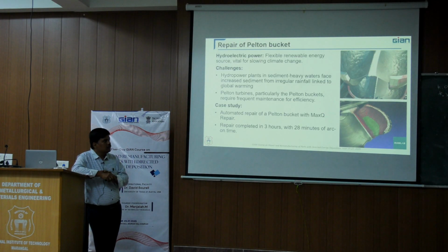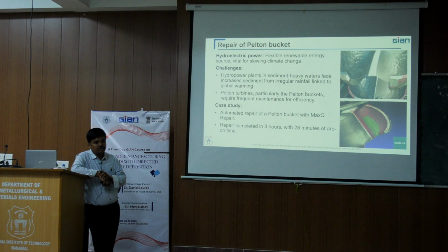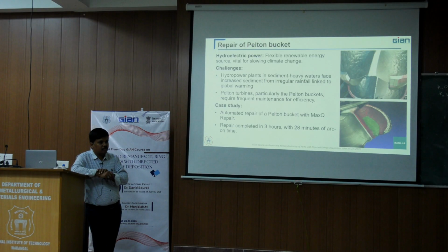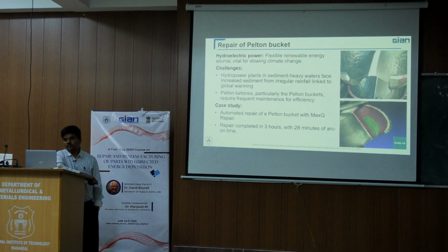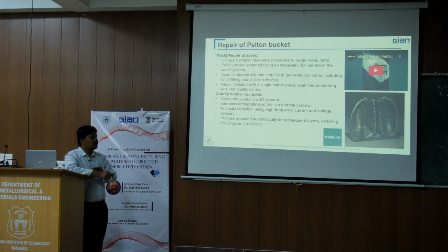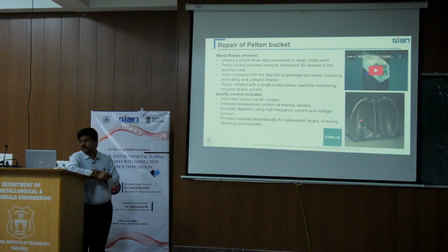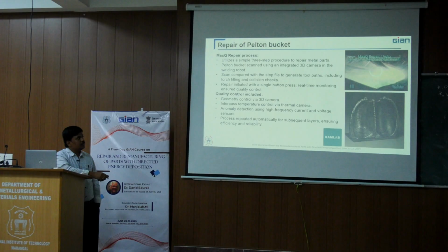Because Dr. Gora told you can take the data, but when you try to repair it, it's going to be challenging, because of how your scan path and deposition strategies have to be deposited. Even during that, it may create some kind of defects also. But that is where they have made a lot of attempts to address, and this can be repaired in 3 hours within 28 minutes of arc time. That's with very minimal cost they have repaired. This is the repaired component. That's how we are able to take the data and repair it.